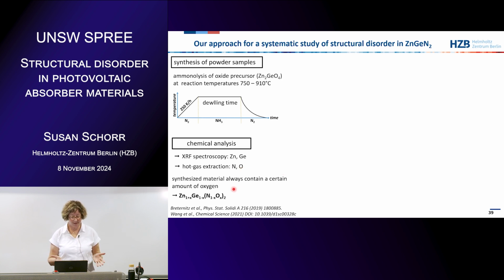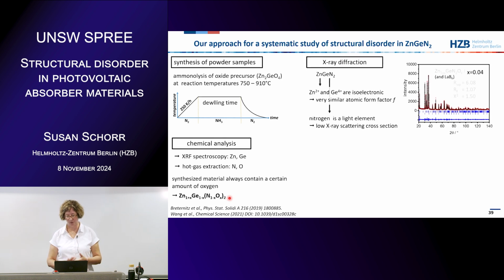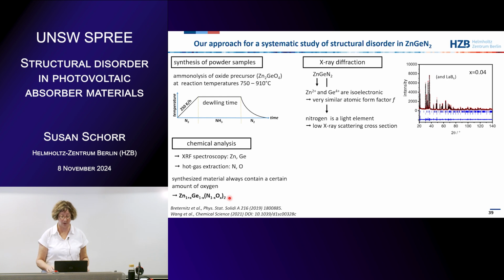And what we found is that we always have some oxygen in the material. So in principle, it's an oxynitride. We never could manage to get the oxygen out. This has some consequences. Then we do X-ray diffraction as usual.